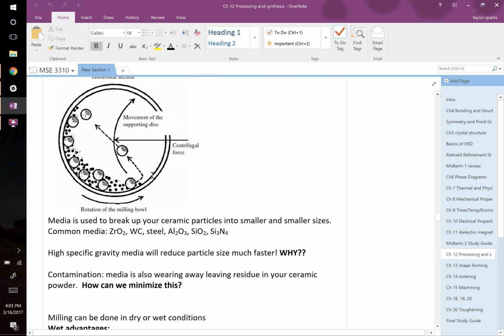We talked about ball milling, that there are roller mills, that there are planetary mills, and that you have to select your media to get the right properties in your final product. That might be that you simply can't stand any impurities. If that's the case, you're going to want to pick a very tough, hard material that's less likely to break off and form impurities. If you can stand some impurities because you're going to remove them later, either magnetically, by dissolving them, or you just don't care about the impurities, then you can get away with other materials. One of the top-end materials is tungsten carbide, but it's going to be very expensive. A cup for a planetary mill can cost $5,000. Pretty expensive stuff, and the media is on top of that, of course.